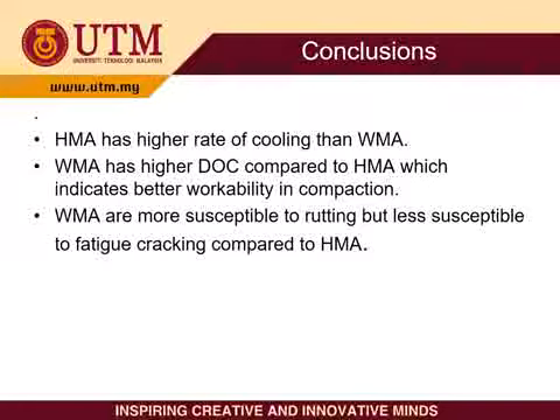First, HMA has a higher rate of cooling than WMA. Second, WMA has higher DOC compared to HMA, which indicates better workability in compaction. Third, WMA is more susceptible to rutting but less susceptible to fatigue cracking compared to HMA.